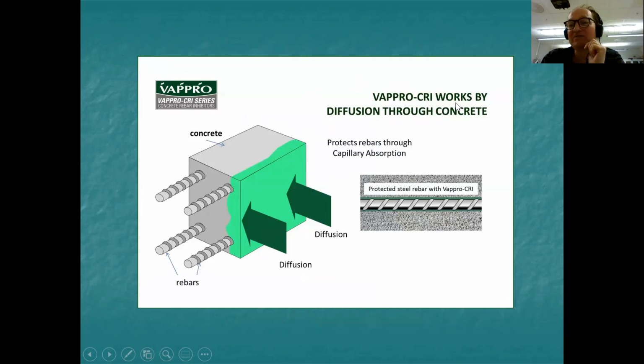So Vappro CRI, this is a corrosion inhibitor, which is based on the volatile method that I'm explaining to you. The material diffuses in the form of a vapor into the concrete, and it forms a protective layer directly on the rebar itself. So because it's volatile, it can penetrate quite a long way into the concrete and far enough to reach the rebars, especially the ones close to the surface, as shown by the green region. There's vapor diffusion going on.